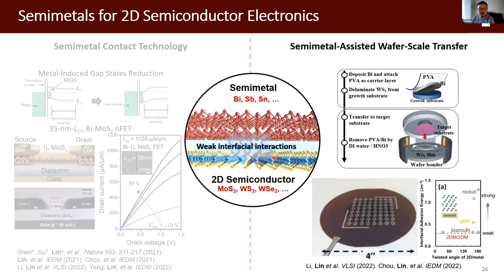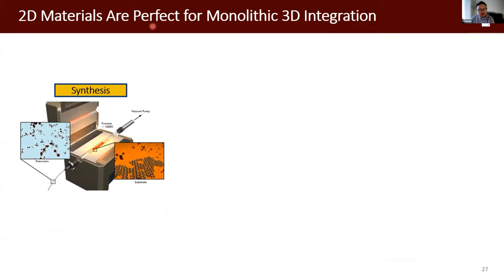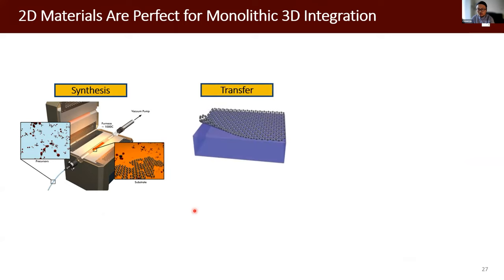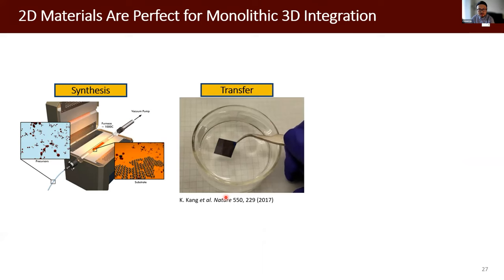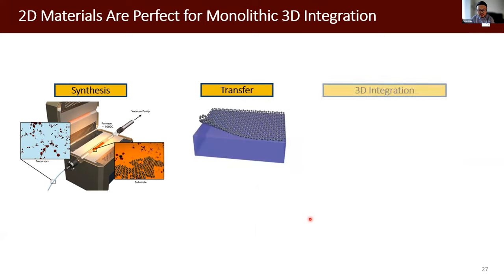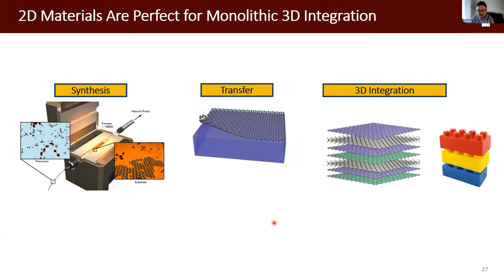So the next topic is, we use a similar effect, but in the chemistry domain, we designed a more scalable integration approach, so we can transfer a wafer scale of 2D materials onto our target substrate in large scale. 2D material is very ideal for 3D integration because we can synthesize them at higher temperature with good material quality. Because of the weak van der Waals interaction, they can be easily peeled off from the growth substrate, and then we can transfer them on top of each other to realize the 3D integration, just like how we stack Lego blocks.